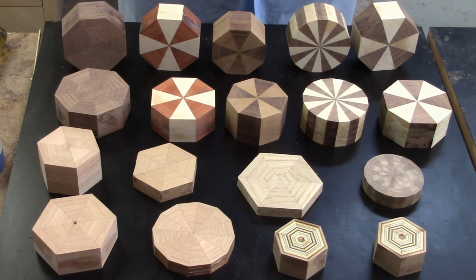These are all segmented rings. The segments were cut utilizing the Accu-Wedge system on the Accu-Slice table, and then they are glued using the epoxy cement. And I will admit I was a little skeptical initially with the epoxy cement. I thought it'd be difficult to use, a lot sloppier, but in reality I'm quite impressed with the results. The glue does have a longer setup time, almost an hour, so you have a lot of time to play with your pieces before they actually set. So if they move a little bit, you can readjust to accommodate any movement of your wood.